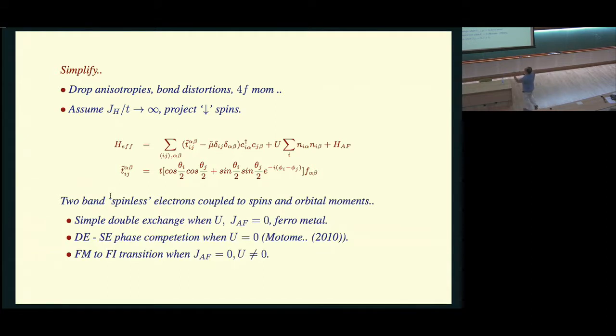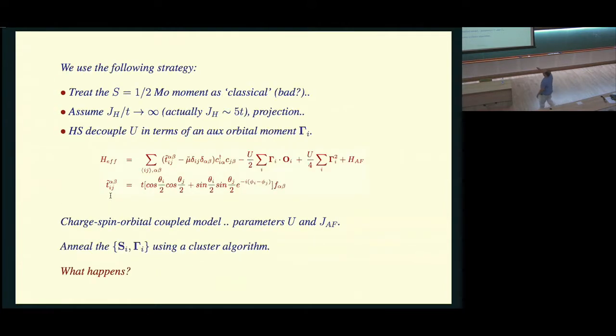Now, in contrast to the older problem where you decoupled the up-down interaction in terms of a magnetic field, here you will introduce what is called an orbital field. So I call something a gamma coupling to the orbital moment of the electrons. So the complicated looking kinetic energy depends on the relative core spin orientations, the orbital moment, my auxiliary field coupling to the electronic orbital variable, and the antiferro coupling. Unlike the older problem, which was a charge spin problem, this is a charge spin orbital problem that you have to solve for a particular choice of U and JAF. So you again go through the annealing process, the Monte Carlo, etc., to anneal the background magnetic moments and the auxiliary variables and try to find out what happens.